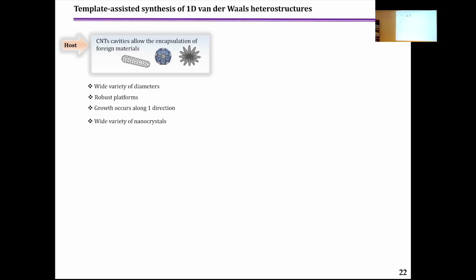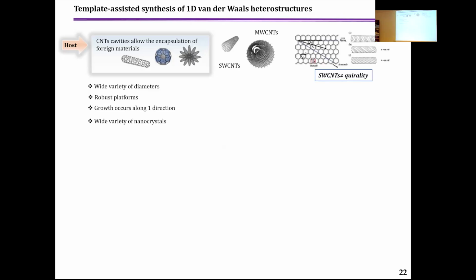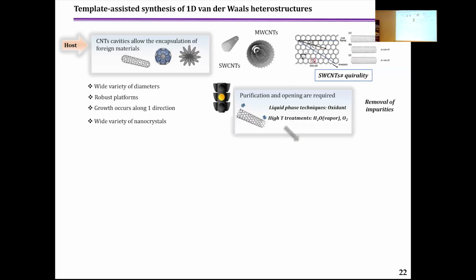The advantage of carbon nanomaterials, in particular of carbon nanotubes, is that they have a wide variety of diameters. They are platforms which are robust. The growth can occur only in one direction. And due to the diameters, they can encapsulate a wide variety of nanocrystals. We can then use single wall and multi-wall carbon nanotubes that can also provide specific properties to the systems. So one issue is that in general, we need a previous purification of the materials because they usually contain remnant catalyst from the synthesis,